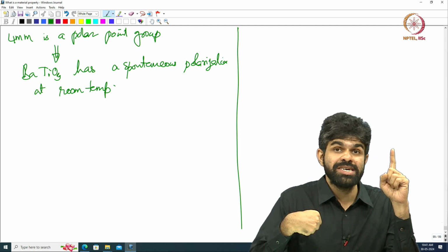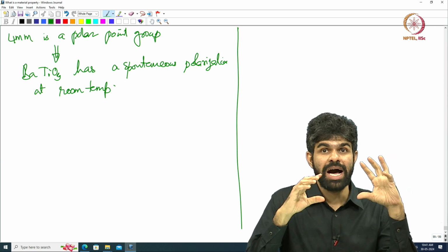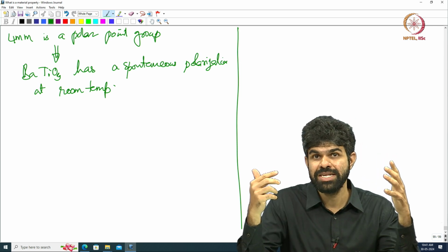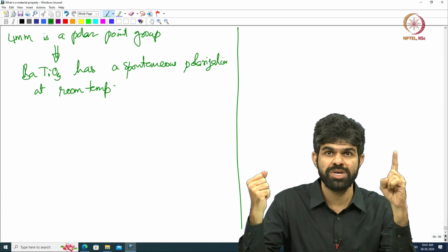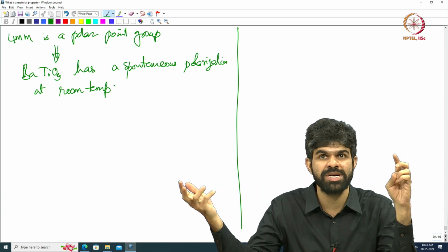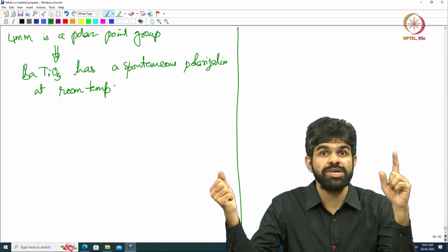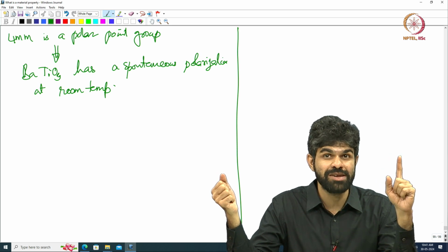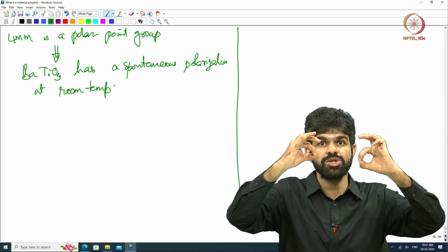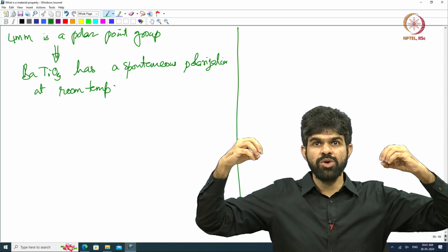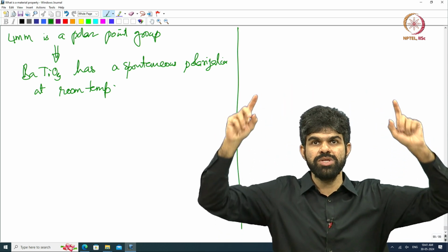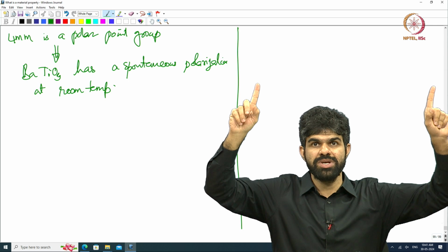Now, barium titanate, also the other part, the electrostatics part, is that there is a spontaneous polarization, but the same spontaneous polarization also comes for aluminum nitride, gallium nitride, etc. But you can call barium titanate a ferroelectric because of this titanium displacement which has gone up. So, when all the titaniums have in coordination gone up, the dipole moment is this way, the spontaneous polarization is this way.